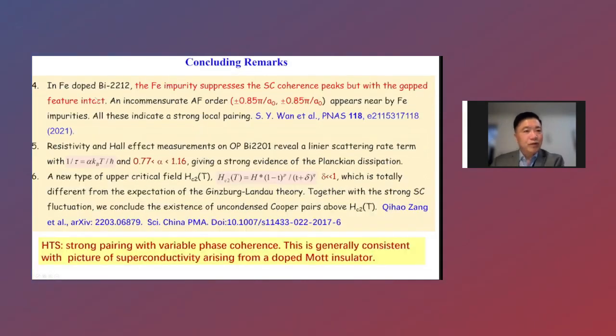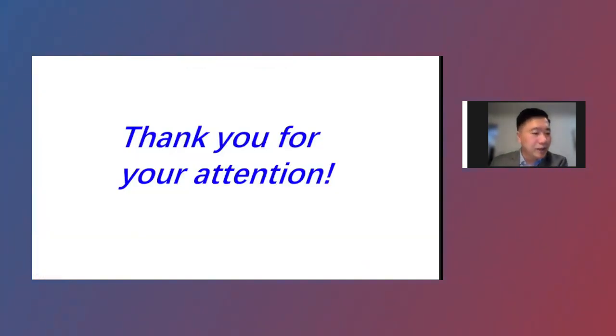Also, in the iron-doped Bi2212, we found a re-emergent antiferromagnetic order with a shorter wave vector, which is incommensurate. With the linear transport data, we found Planckian dissipation. And we also found a vortex Nernst signal, which is not the Ginzburg-Landau type, but shows uncondensed Cooper pairs above Tc. So all this data shows that we have strong pairing with variable phase coherence. This is generally consistent with the picture of superconductivity arising from a doped Mott insulator. So with that, I thank you very much for your attention.